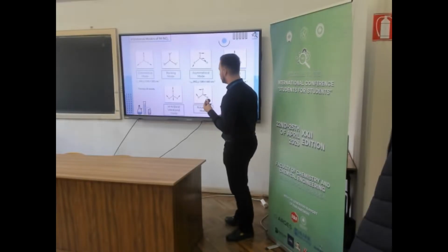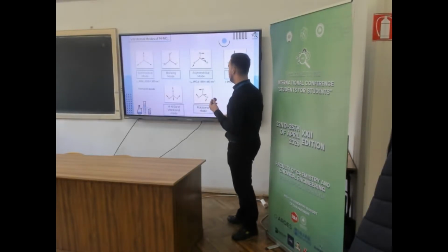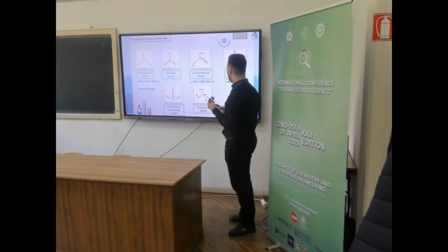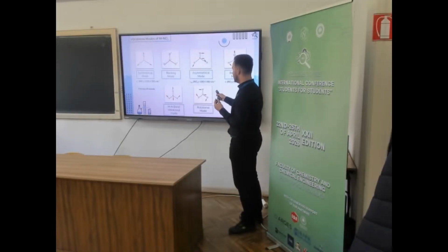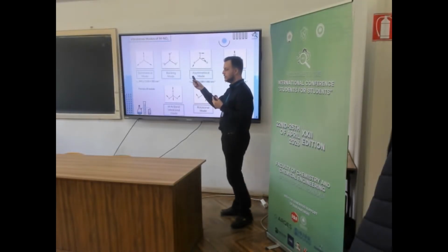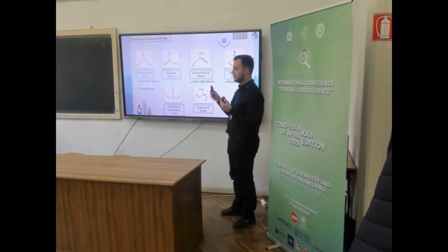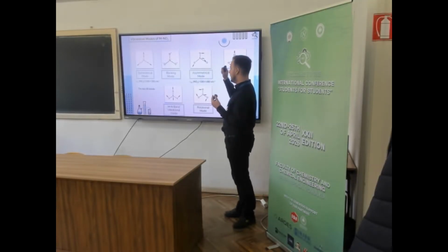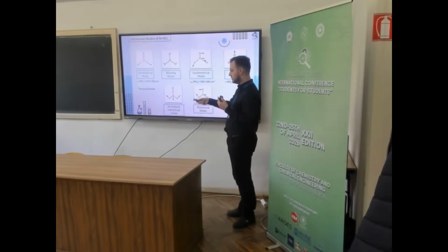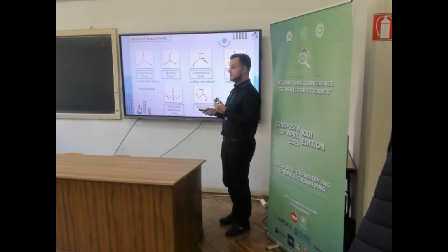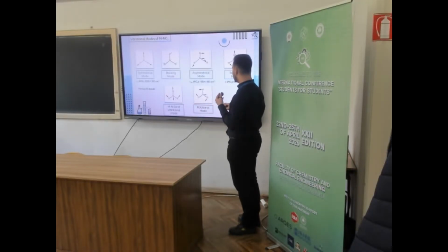For a brief introduction to the vibrational modes of the ligand, because we will get into the IR spectrum, the most common ones we can find are the bending mode, symmetrical mode, and asymmetrical mode, which you can see the values that they appear in. The rocking mode presents itself as a very low intensity band at 500, 600, and the vibrational mode for the metal-nitrogen bond, in some complexes, is present at 400, 420, but it's very common that you can find it at 200. So we will not see it in most complexes. The same goes for the rotational mode.